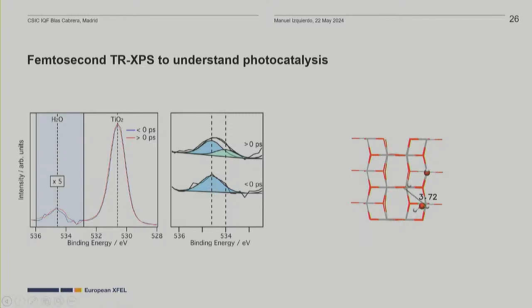And let's see if this works. So basically, you start with this system where water is on a titanium 5C site, and then you see what the interaction is going to do as a function of time. What is going to happen is that a bond is formed between the hydrogen and one of the oxygen 2C sites, and this reduces the distance from the 3.72 that we saw at the beginning to 1.72, and this allows explaining what is happening in the system.